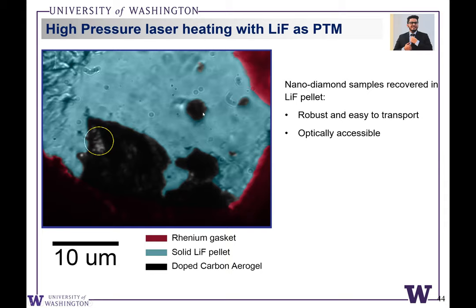Also, I wanted to share some really exciting recent data that another group member of mine, Chaman Gupta, has made recently. Instead of worrying about argon doping in our diamonds, Chaman and Abby have been working closely together to translate to lithium fluoride as a pressure medium. It's not nearly as quasi-hydrostatic as neon or argon, but it has the advantage that we can melt lithium fluoride and encapsulate the diamond materials within the culet itself. And then we can take the gasket to another facility, whether that's an atomic force microscope or a low temperature optical cryostat, to do spectroscopy and physical property measurements of these diamond materials that we've made.